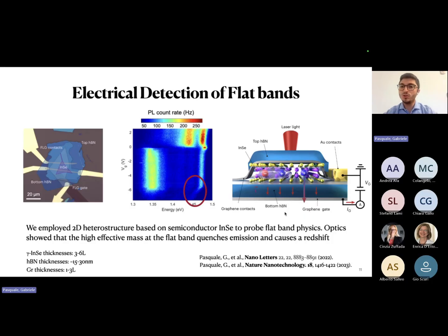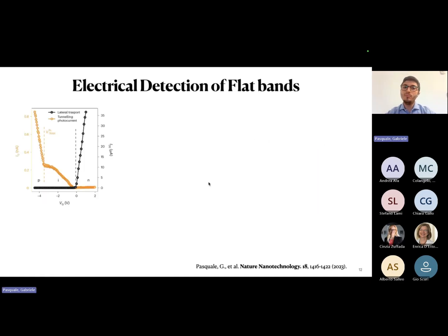But later, we decided to focus on out-of-plane tunneling currents, which turn out to be an extremely valuable tool for this purpose. When I say out-of-plane tunneling currents, I really mean currents that go from the indium selenide through the hBN to the back gate of graphene. When we look at the in-plane transport in black compared to the out-of-plane tunneling current in yellow, we see that at the hole side where the flat band is located, the transport doesn't really show anything meaningful. However, the tunneling current, in this case tunneling photocurrent, shows a very sharp increase at a very specific point.